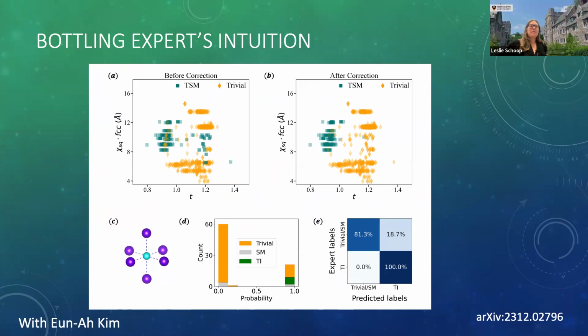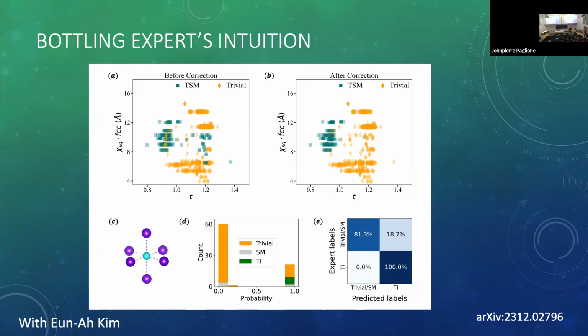Yeah, that's a good point. So this is actually an element-specific parameter. It's one number for each element. You can calculate that, and it will show you that it has the region here which is good, which is between two extremes, not too large, not too small. It will be highlighting all main group elements, which makes a lot of sense because we were talking about bonding, and these types of covalent bonds are more typically made by main group elements. It's a pretty narrow range of numbers. In our paper, we have a figure with the number printed on the periodic table, and you see exactly the elements written there.